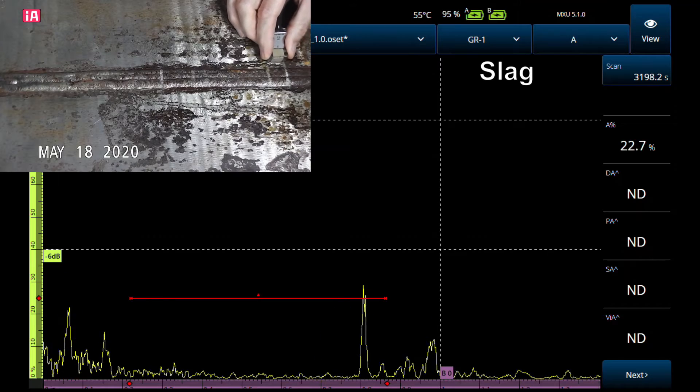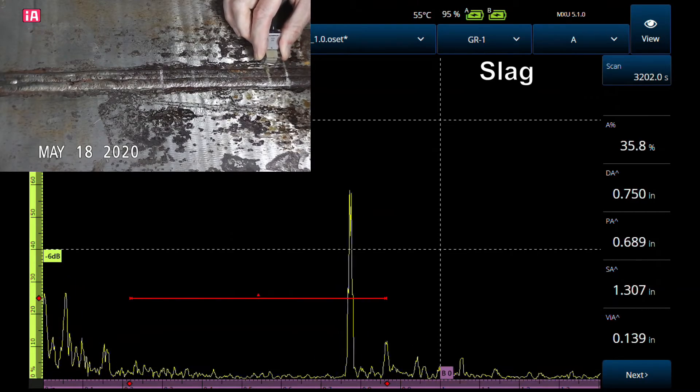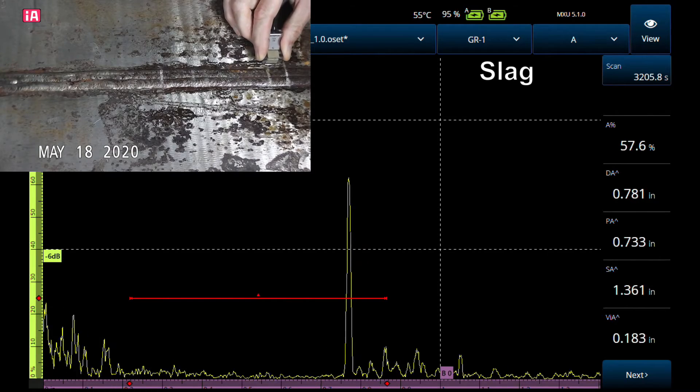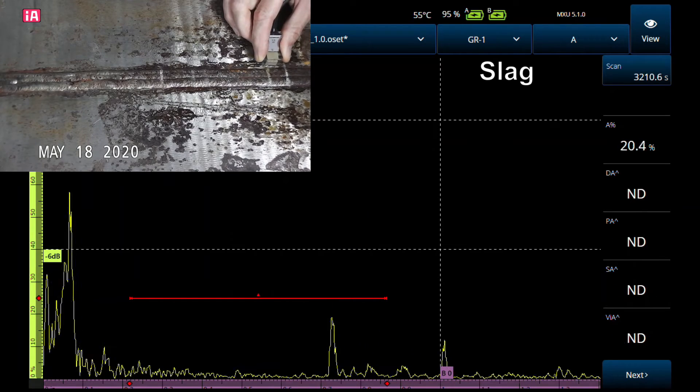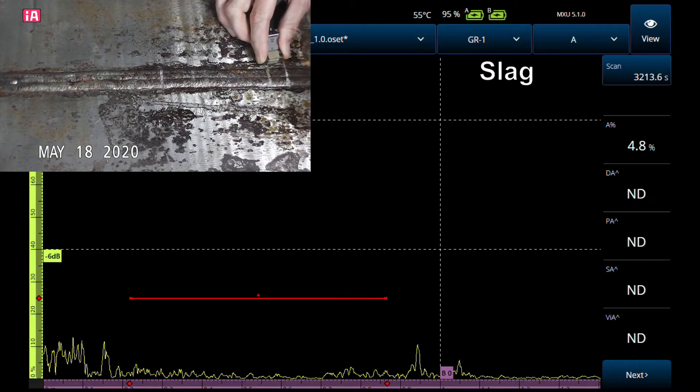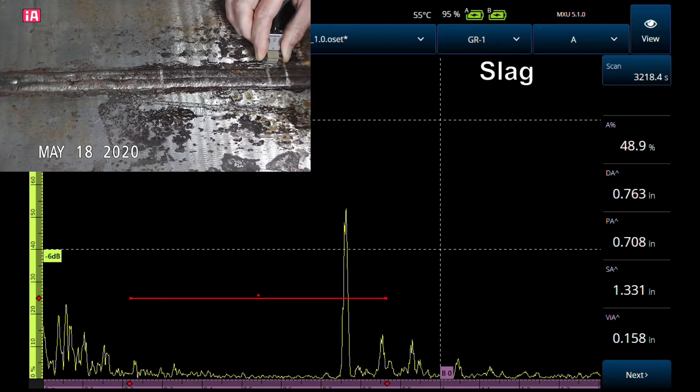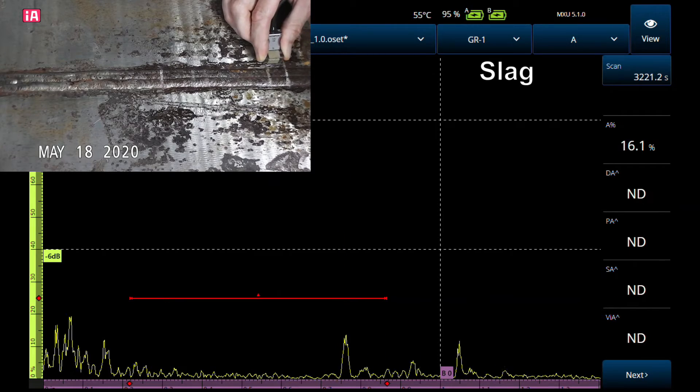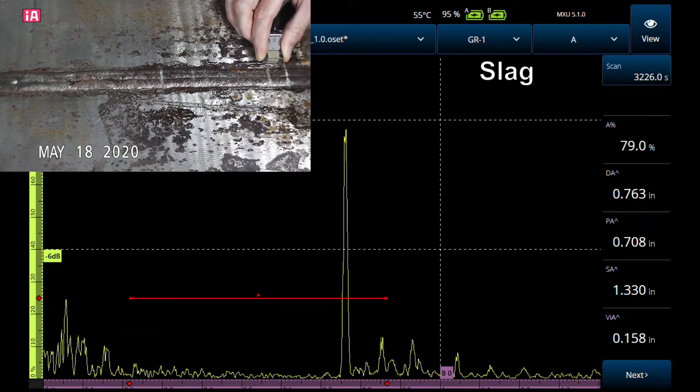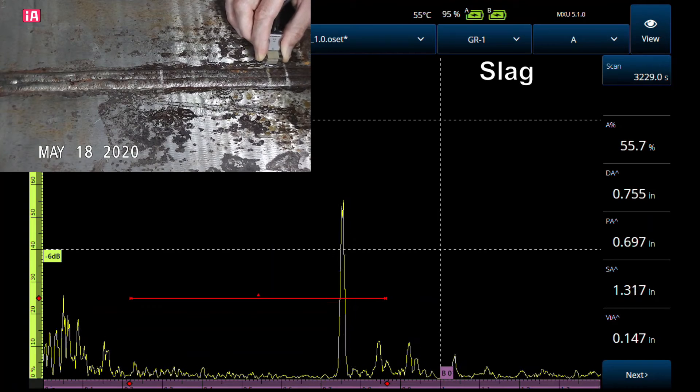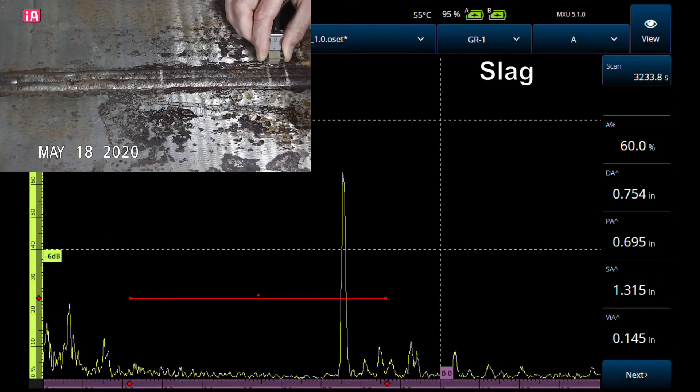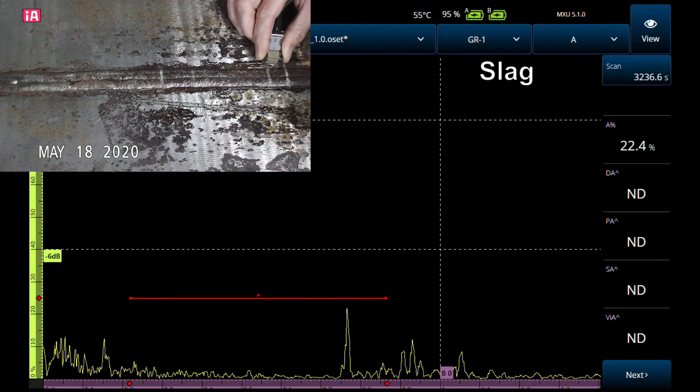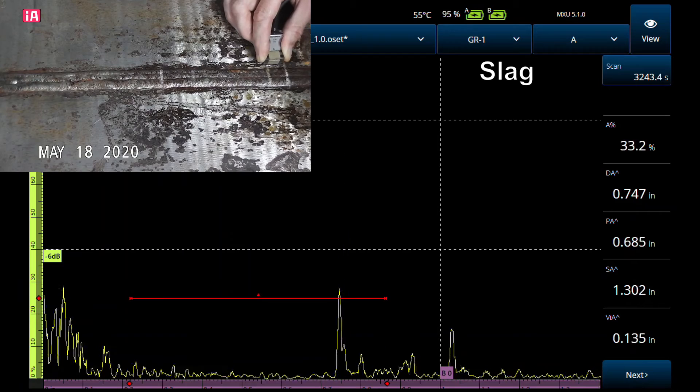Let's get the signal on here. We want to go toward and away from the weld and see what happens. You can see that's not got a lot of height to it. We want to skew the probe, which is twisting at an angle like this. That will reveal any kind of roughness and help you with the orientation of the flaw. You can see it's pretty much right along the length of the weld. It's not a real smooth reflector because when we skew it, that signal kind of stays on there quite a bit. See how much the probe is skewed right now—we still have a signal on the screen.